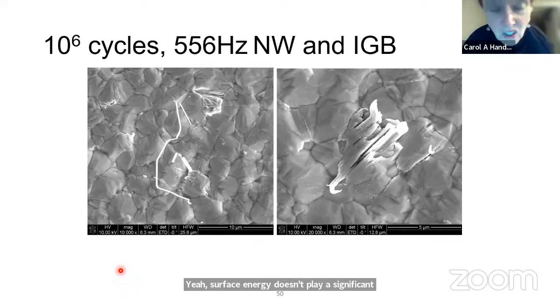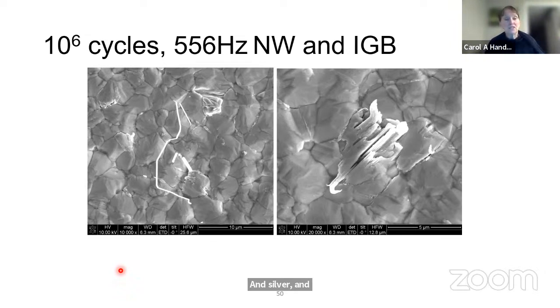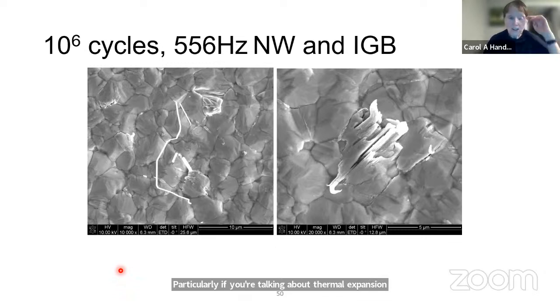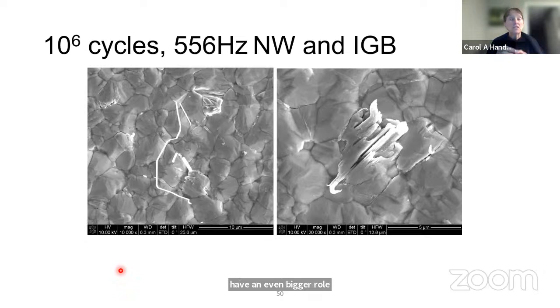The other thing is that this happens in gold and silver, and there are conditions where we can make all of these happen in different systems. So I think the surface energy is a small component, particularly if you're talking about thermal expansion mismatches, because you can generate really large stresses due to the thermal expansion mismatches between the thin film and silicon, or gold and silicon. So those, I think, have an even bigger role to play. For example, in making the grain boundaries of the small surface grains, the grains grow, and it's very much like the abnormal grain growth problem.